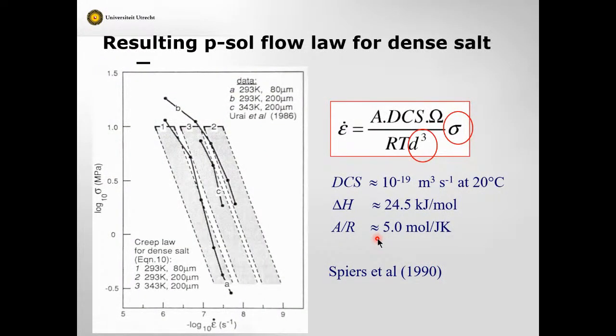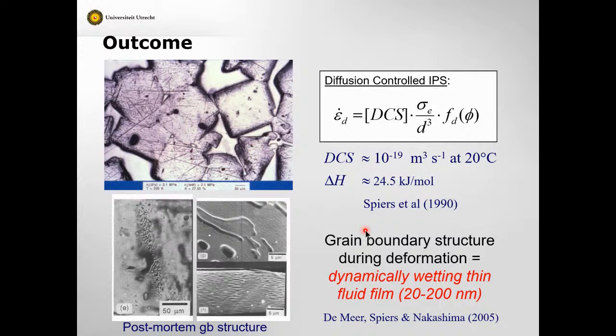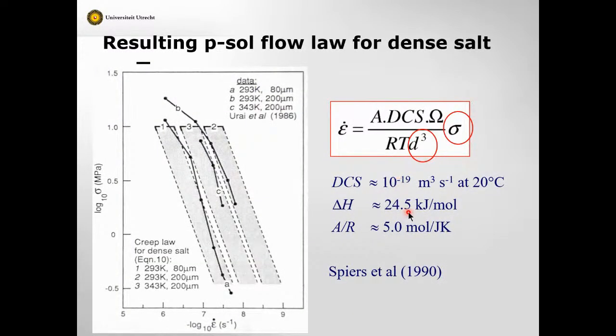We used that compaction data to predict the behavior of dense salt. So this was for granular salt, porous. We used the theory to apply these parameters determined from compaction in creep experiments on dense salt. And we compared it with the original experimental data we had. This was our experimental data for dense salt, and the gray bars are actually the predictions from the compaction experiments. So we got very, very good agreement indeed, and quite high confidence in the values of the parameters in this equation describing the process.